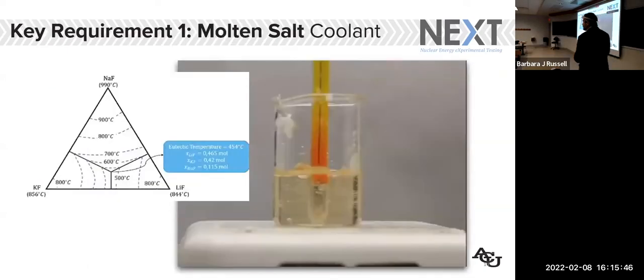But of course, we're not using sodium chloride for our salt in our reactor. We're using a eutectic mixture. One of the cool things about the salts is that if you take the right mixture, this is an example for FLiNaK, so lithium fluoride, sodium fluoride, potassium fluoride, each have a melting point of 800, 900, 800 degrees plus. But if you get the right mixture, you can get a melting point that is something like 450 degrees centigrade. And so we take advantage of that to give us a material that has a lower melting temperature. And FLiNaK, you raise the temperature, it then flows and looks a lot like water. All right, so molten salt is our coolant.